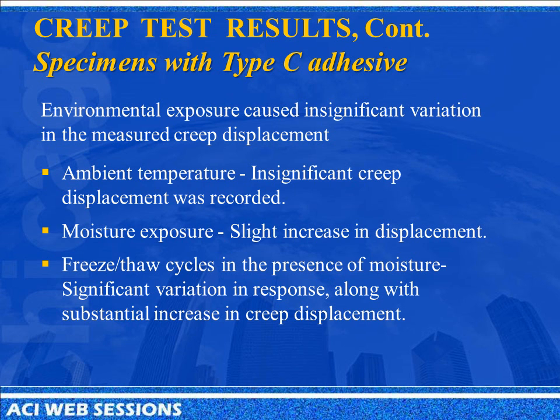So for type C, which is the standard set, epoxy-based, we've seen insignificant creep displacement at room temperature. When moisture is introduced, slightly increased. When freeze-thaw is introduced, again, slight increase in creep displacement, but this time we got some inconsistencies.